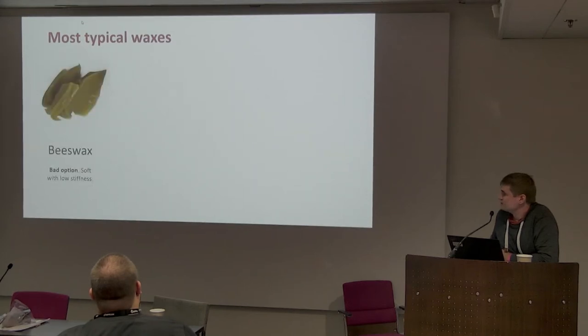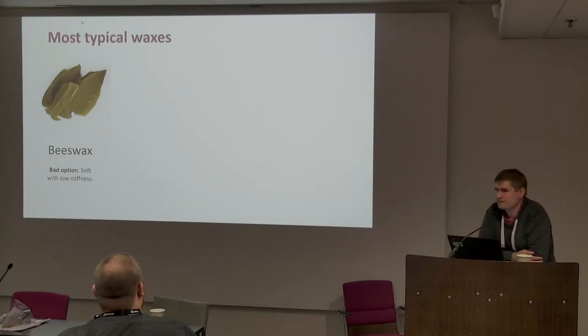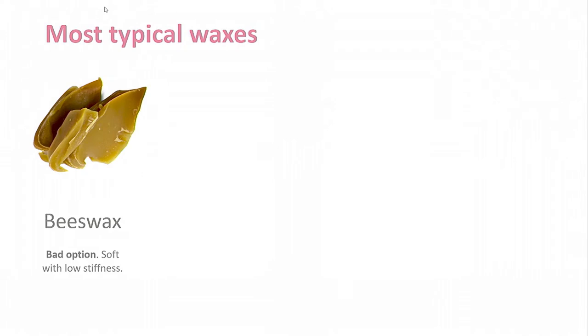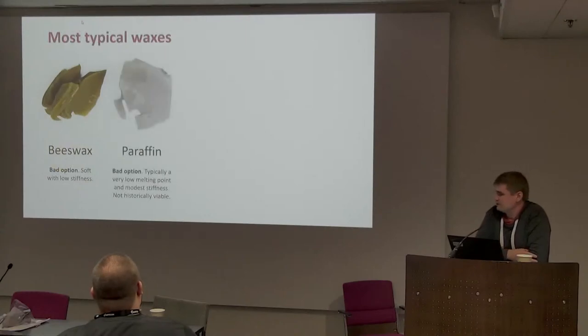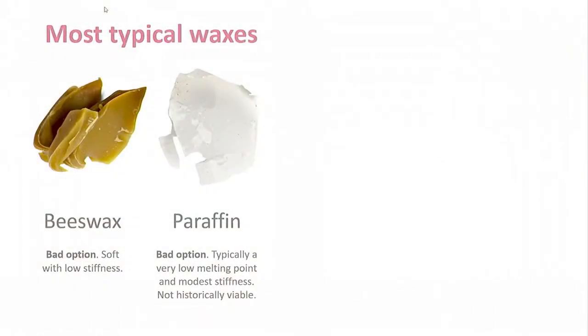Most typical waxes are beeswax, which is a poor option for stuffing leather. Don't use this. It produces soft and not very stiff leather. I was actually shocked when I started making some material tests how bad beeswax is as a stuffing agent. But this is kind of the popular choice because it's viewed as historically viable, but mechanically a very poor material. Then we have paraffin, obviously not a very historically viable material. But in addition to it not being historically viable, it's also mechanically a really poor material to stuff leather with. So avoid at all costs, don't use paraffin when doing leather armor, period.